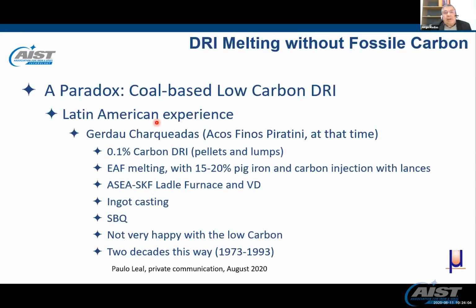And in Latin America, we have had 3 plants, 5 units: Gerdau Charqueadas, what used to be Aços Finos Piratini, an SBQ producer; and Siderperú and Aceros Arequipa, both in Peru with 2 units. Regarding Piratini, they had DRI from pellets and lumps, EAF melting with carbon from pig iron, as is usual in Brazil, and carbon injection with lances. Then further treatment in ladle furnace and vacuum degassing, ingot casting, and SBQ. They were, of course, not very happy with that low carbon 0.1, but they worked for 2 decades this way, till the DRI plant was idled. So 2 decades with low-carbon DRI.